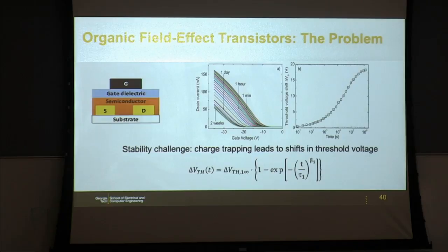So when they operate, after a while, you have some carriers that get trapped either in the semiconductor or at the interface between the semiconductor and the gate dielectric. And that charge trapping, which can be described by a stretched exponential equation like this, is something you just have to live with. You can minimize it, but you can't get rid of it. Okay? So you can just pick the right material platform and hope that the threshold voltage shift is small.